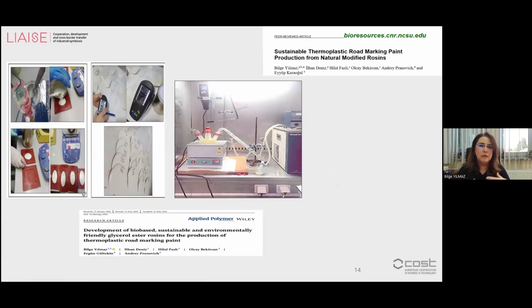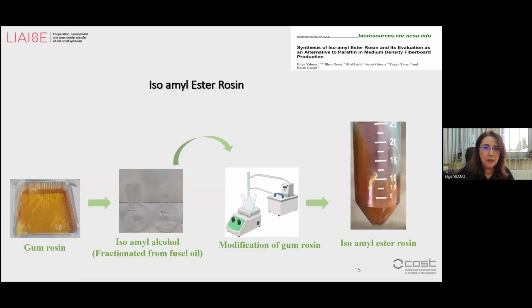thermoplastic road markings. We succeeded, and we have 2 papers about that. Also, you can see the instrumental setup of the esterification reactions. Also, we use inert atmosphere, and we use a mechanical stirrer, because the rosin is very viscous in the reactions.